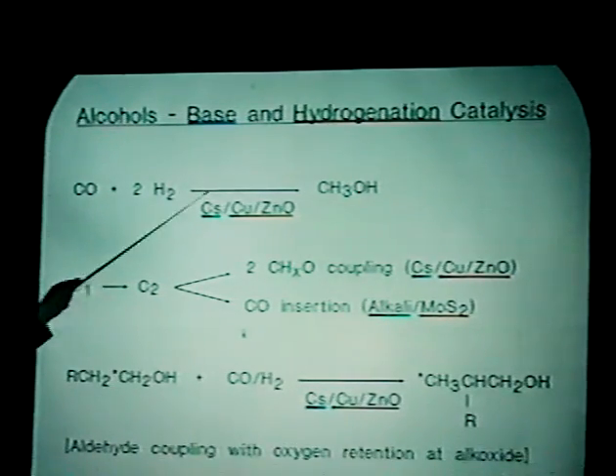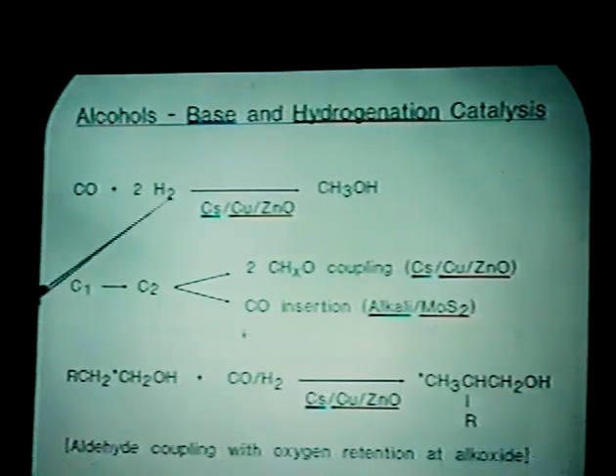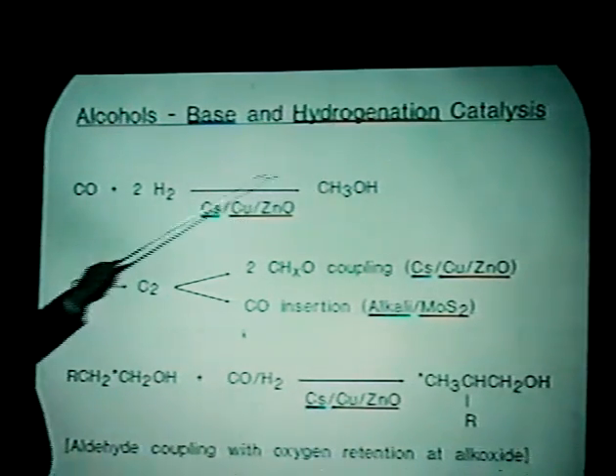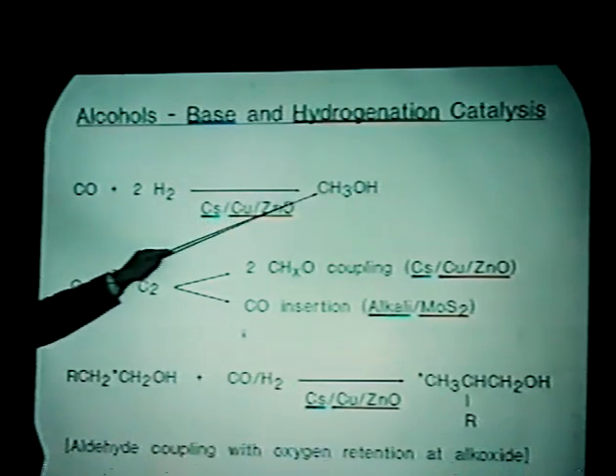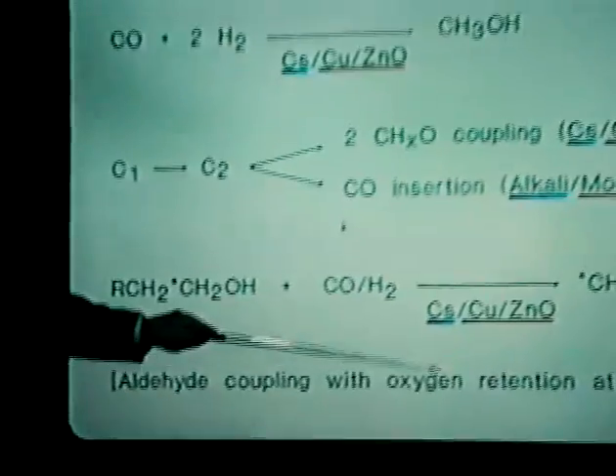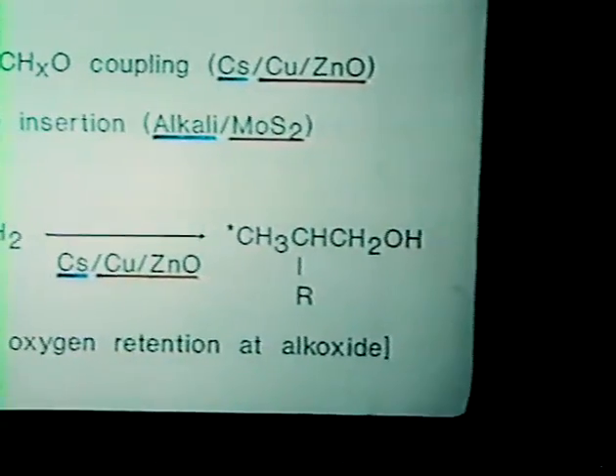Well, if you believe that this goes against the patent literature, we did discover that the rate to methanol is enhanced and selectivity is retained in the presence of these heavy alkali. And in the higher alcohol synthesis, we are getting the alcohol that goes counter to the textbook aldol result. That is because we are carrying out the reaction so that we are pinning the alkoxide group on the alkali ion and allowing the carbonyl group to be hydrogenated before the alkoxide group hydrolyzes.